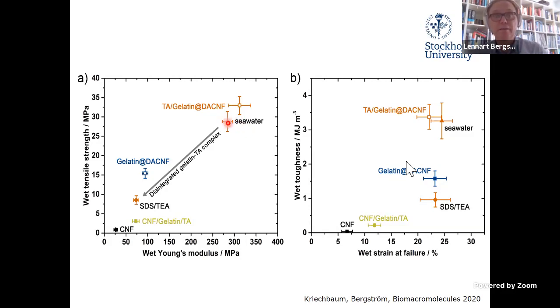But we can disintegrate this material by adding a surfactant, sodium dodecyl sulfate, together with a solvent, which disintegrates the gelatin-tannic acid complex, bringing it back basically to a similar strength and modulus as the mixtures of CNF, gelatin, and tannic acid.